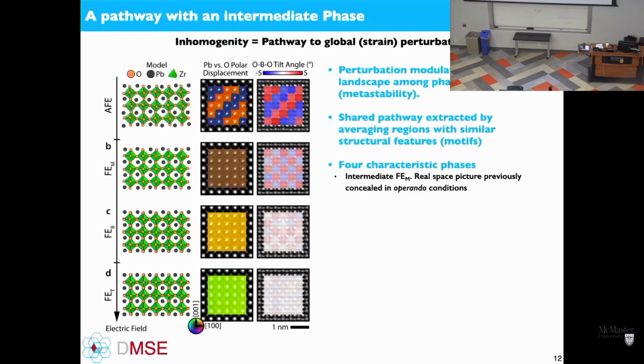But one thing that we found, and one key thing at the atomic scale, is that you can map out some of these phase transitions. So what we'll find is that initially the sample starts out antiferroelectric. As we begin applying a field, the polarization begins to rotate such that you get this polar order that starts to pop in. It's ferroelectric but monoclinic. That monoclinic phase gives way to a rhombohedral phase as the polarization continues to rotate into the field direction. And then at full field and full transition, you go to the tetragonal phase.